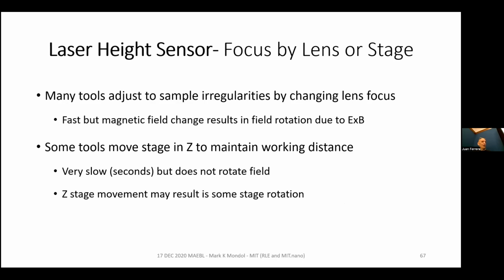We also need to have good focus. So how do we have good focus? By knowing the distance from the substrate to the final lens. And the way we can do that is by having a laser that bounces off our substrate onto a linear detector. And that point at which it hits that linear detector tells us the distance. And therefore, we can change the focus.